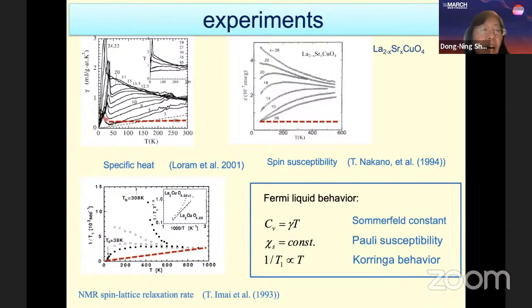For example, the coefficient gamma has an almost linear T dependence above the critical superconducting temperature. At the same time, the spin susceptibility also depends strongly on temperature, and the 1/T1 behavior is also different from linear T dependence.